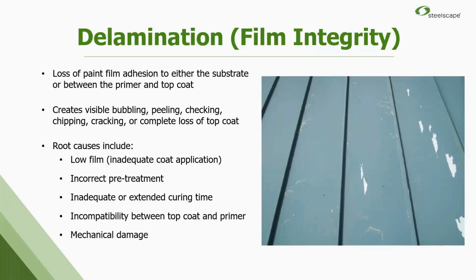The most common root causes for this are low film. So that's on us, the coater, for not having put enough paint on. The pre-treatment may not have been right. Maybe we didn't cure and dry the paint properly. And that's a fun one because if you under-cure the paint, it's going to do this. If you over-cure the paint, it's going to do this. We have a very tight window in between the two we have to hit. Could have been an incompatibility between the top coat and the primer that long-term is not holding up.